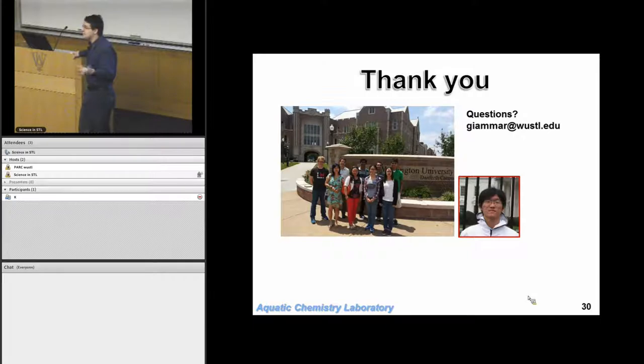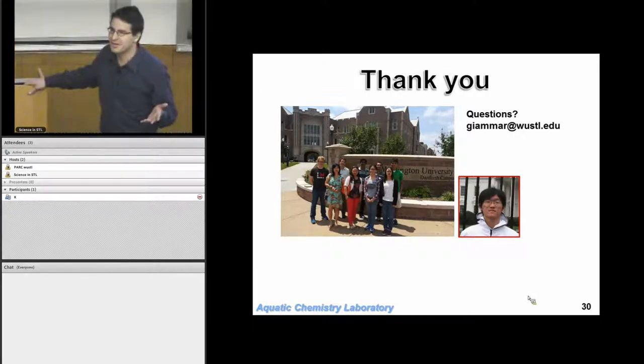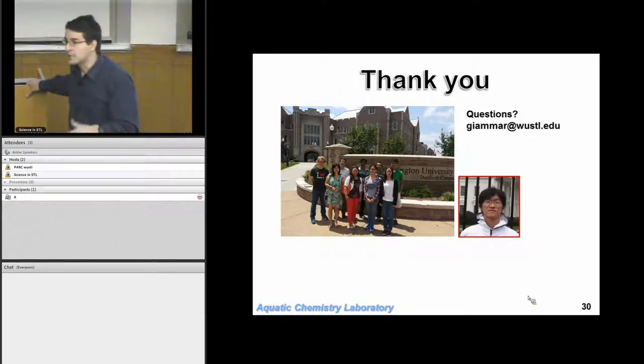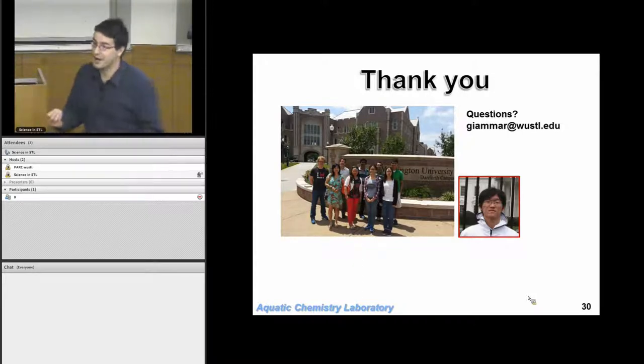In the United States, best practices for fluoride removal would usually be adsorption onto activated alumina. It works. It's not particularly efficient. You have to use a lot of adsorbent in order to get the fluoride down. Some of these iron-based technologies could work for removing fluoride. I know that Professor Chowdhury has some data on that. One that's a little bit interesting on this, because it relates to some challenges of where you're working, is that phosphates can remove fluoride pretty well. So phosphates are actually pretty good for getting fluoride out of your water.